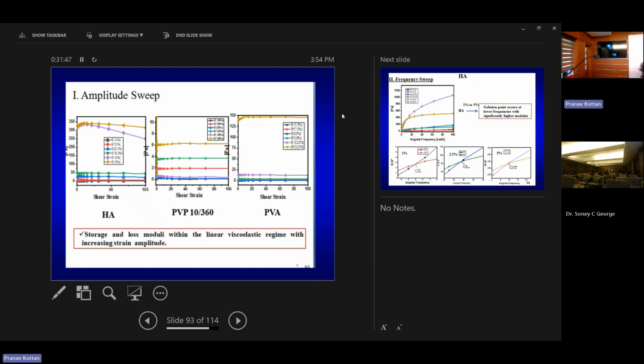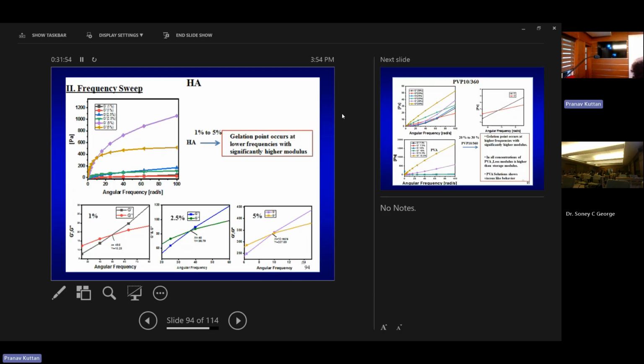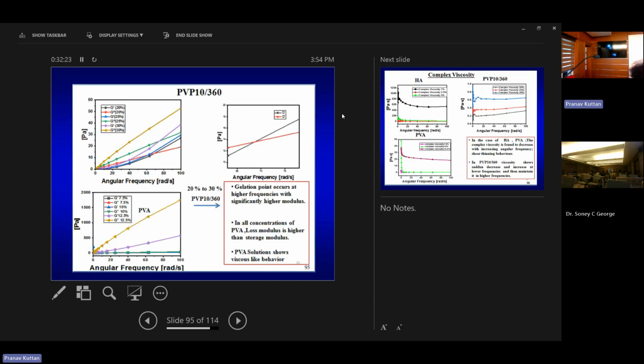First we did the amplitude sweep, to see how the strain behaves. We found out the viscoelastic regime. Then we did the frequency sweep for different concentrations of HA. We found that the gelation point occurs at lower frequencies, with significantly higher modulus for hyaluronic acid. Thereby, we wanted to see how much handling time we can get before gelation happens. Then for PVP 10/360, the gelation point also occurs at higher frequencies in this case, with a significantly higher modulus. The modulus values are higher. But in all the concentrations of PVA, this is actually PVA, here we found that the loss modulus is higher.